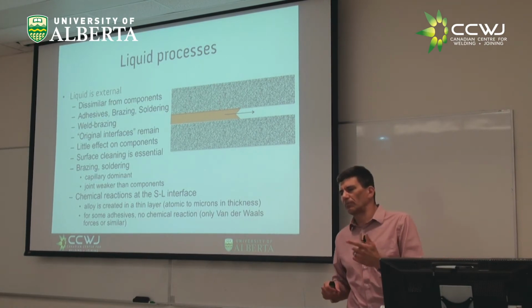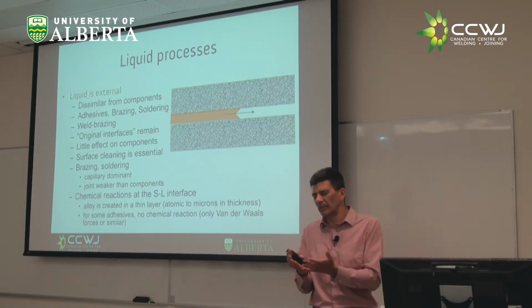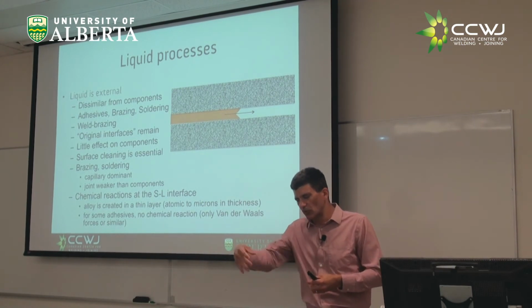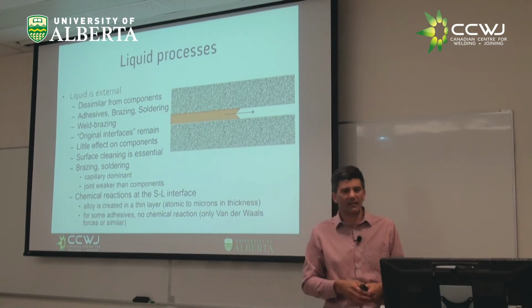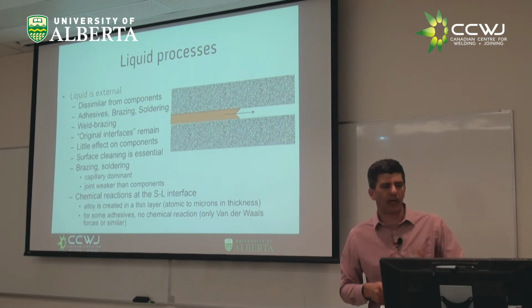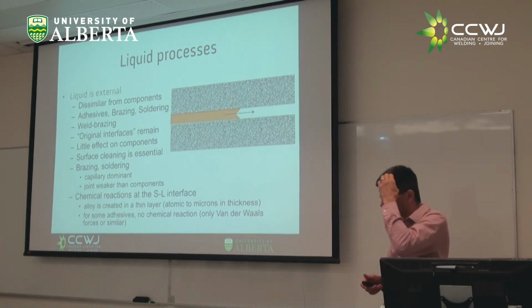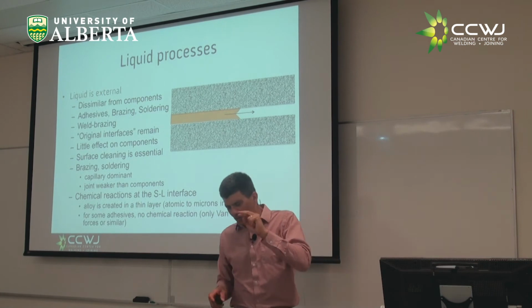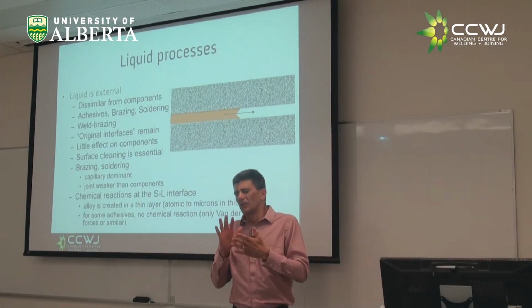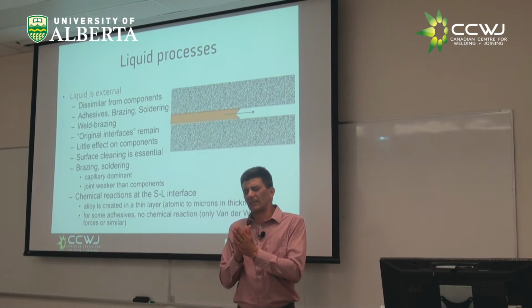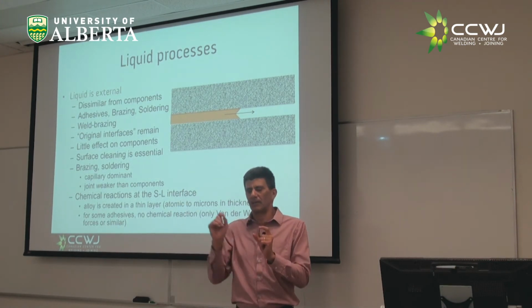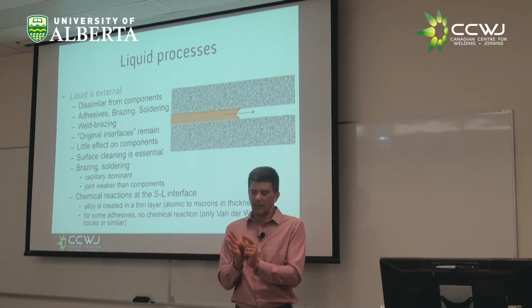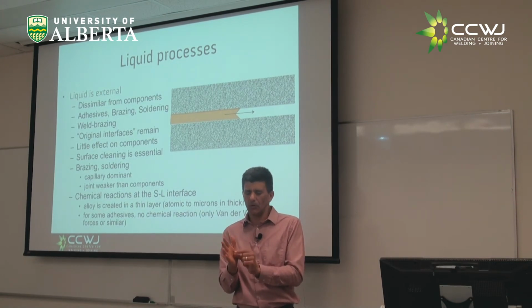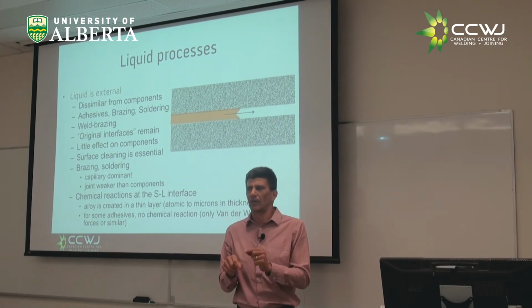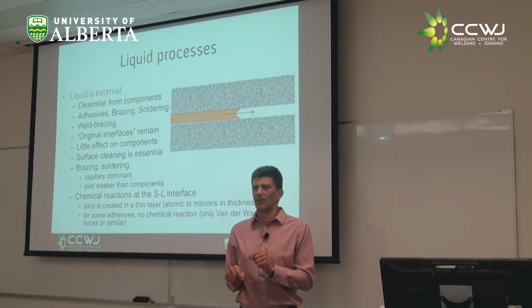Brazing, soldering, there's something called weld brazing in which you're not actually welding the parts, but you're using a welding technique. So you melt the metal and it's going to have this glue type effect. The original interfaces remain, but I put it in quotation marks because really between the interface, in the case of brazing or soldering, in the interface between this liquid you put in the case of a metal, and the metal structure you want, for example, the copper pipe and the solder, right at that interface there is a chemical reaction.